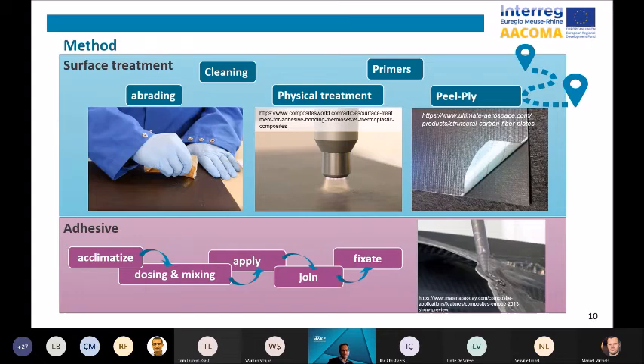Once the surface treatment is defined, you have to define a method to do the bonding itself, and a complete process has to be defined. The correct method of mixing, how much adhesive you will prepare at once, applying the adhesive, how to cover the complete bonding area with no air entrapments, and how to join and what tools are needed. And in the end, within the work life or pot life, how to fixate, and maybe possibilities to speed up curing by adding heat. For the last step, a big remark: do not move the substrates after fixation. A common mistake is to just reposition the parts a bit after the pot life, and this will lead to a very weak bond.